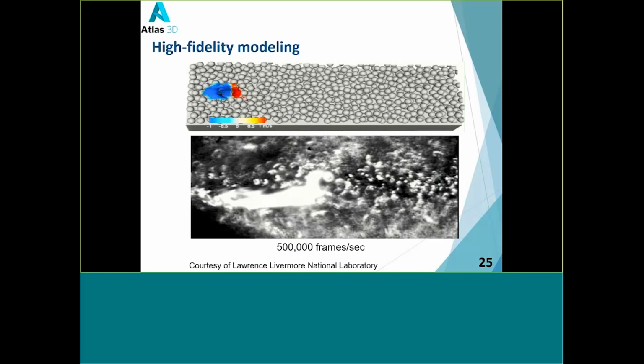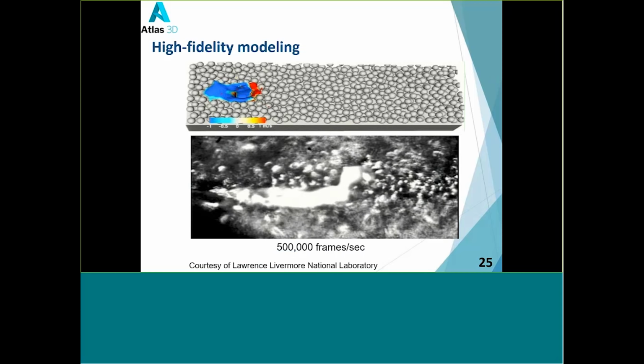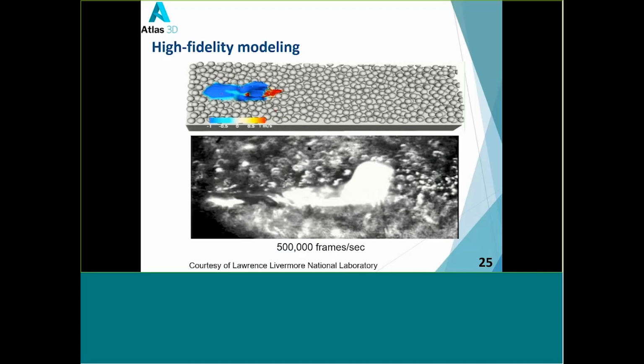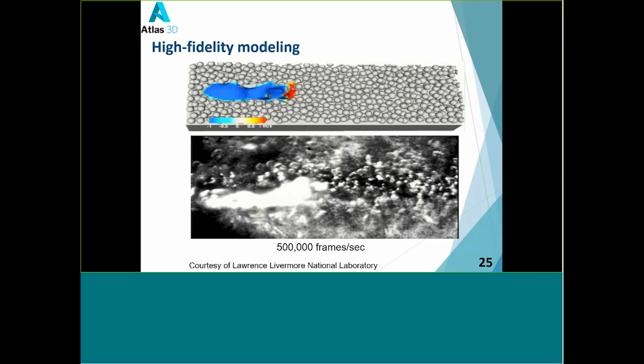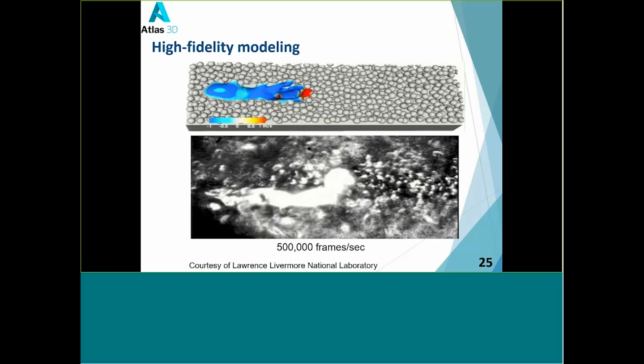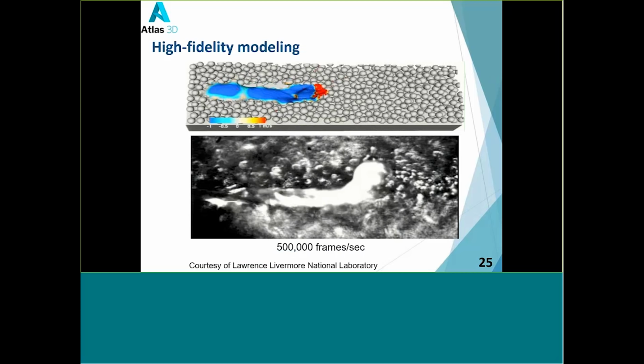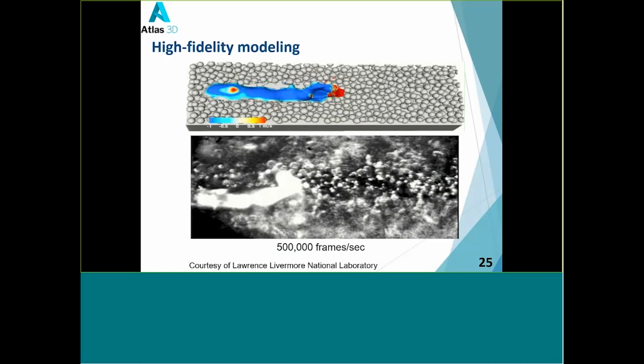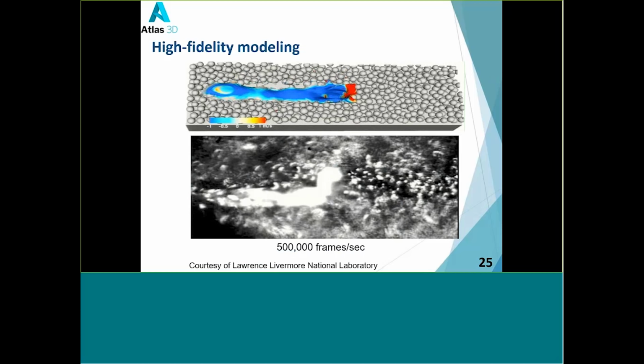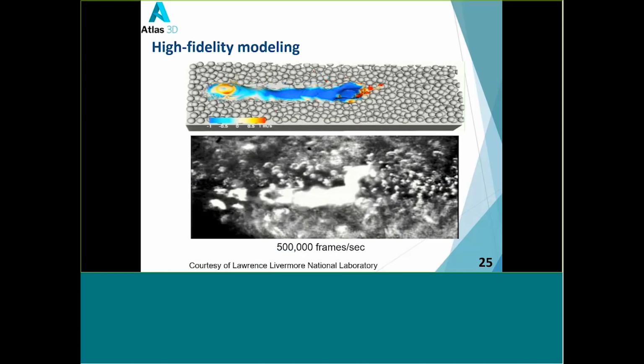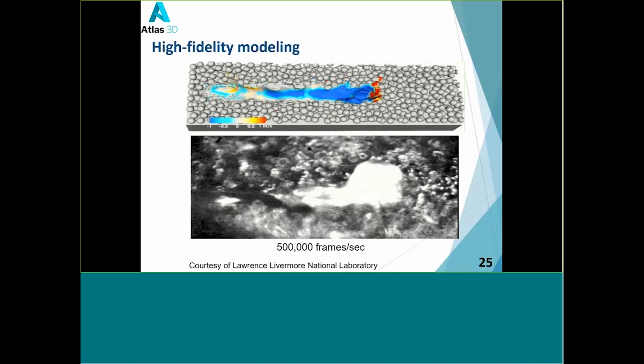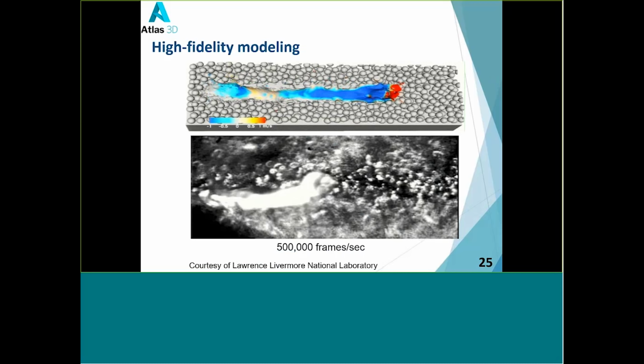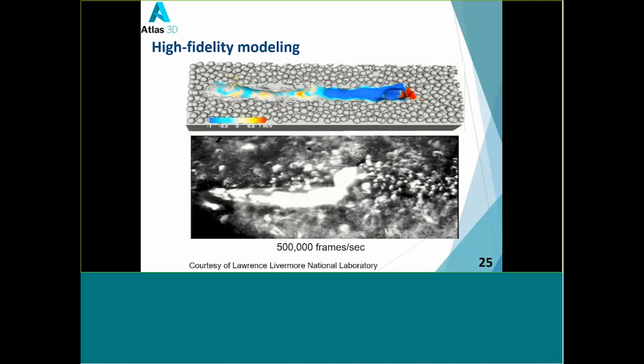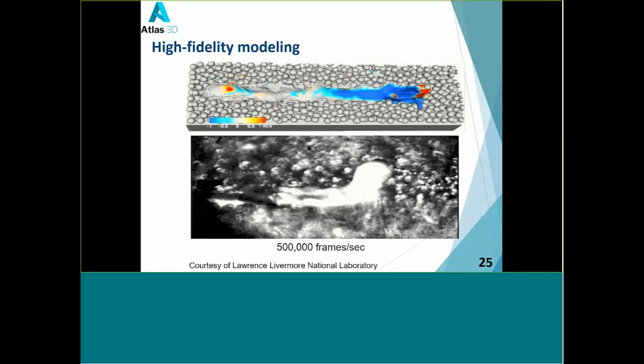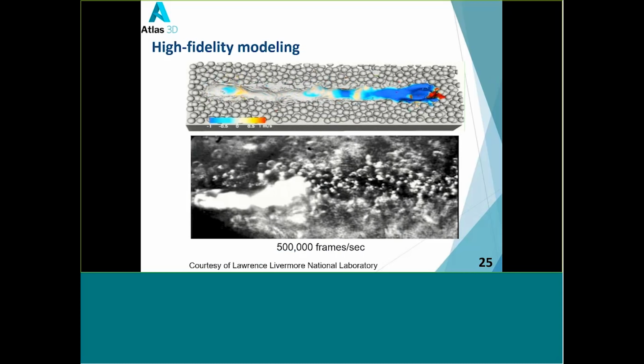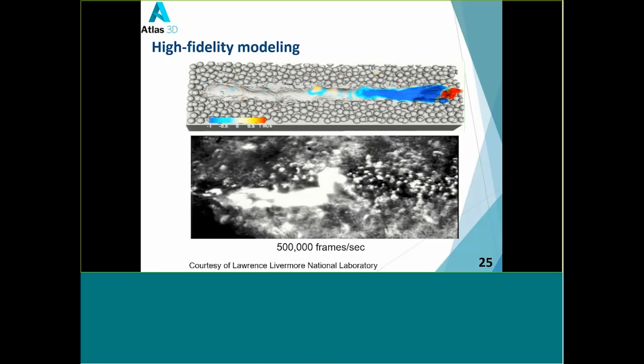Here, what I show you is the high-fidelity modeling conducted by Lawrence Livermore National Lab. You can see that they model each single metal powder, and they model how the laser beam scans through the metal powder and how the metal powders are melted. And you can see the dynamics of the fluid flow. You can see the surface tension effect. So this model includes almost all the physics happening in the AM process, and it compares very well to the experimental observation.